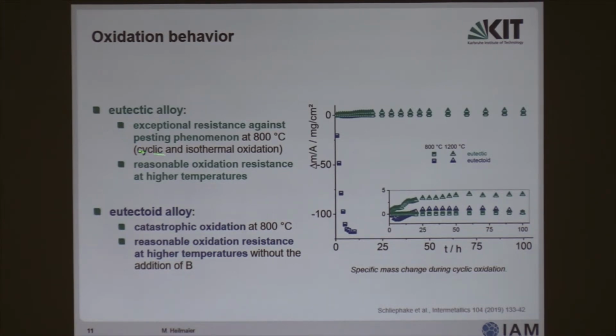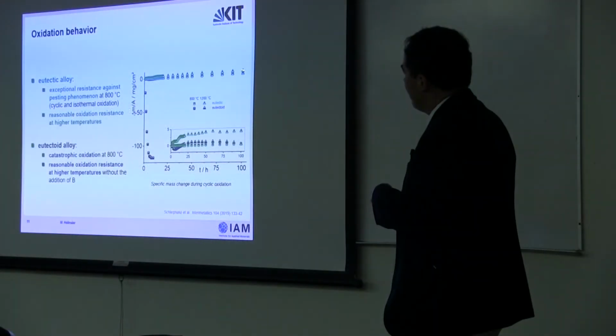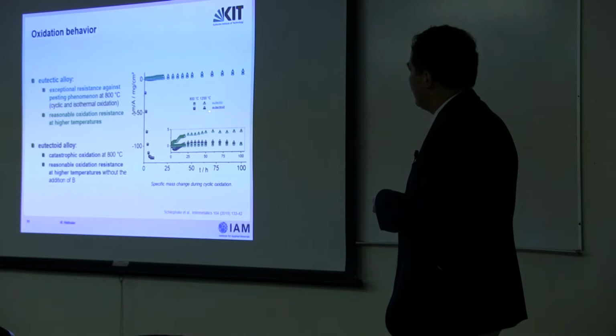What this means is when I put this alloy in a furnace, I have shown you two different temperatures, 800 degrees Celsius and 1200 degrees Celsius. Green is the eutectic alloy, the blue color is the eutectoid alloy. And what you see here, the green alloy, the eutectic alloy, does not change its weight. Here is plotted the weight per surface area, delta M over A in milligrams per square centimeter. If the weight does not change, this is an indication for a very slow oxide formation at these temperatures, right? However, compared to that, and here you see three curves plotted. Well, the third curve you cannot see because it's the eutectoid curve at 1200.